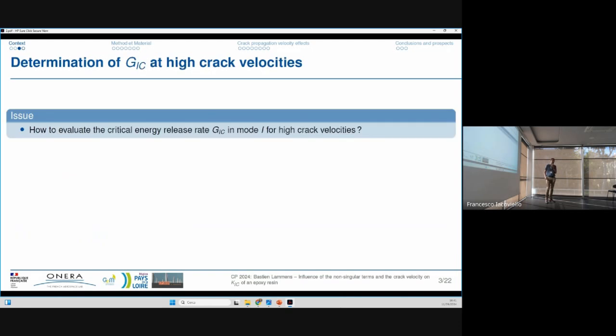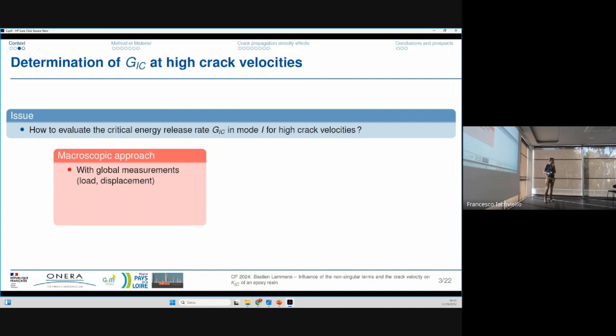So the question during my PhD was how to evaluate the critical energy release rate, G1C, in mode 1 for high crack velocity, because we want to have high crack velocity when we have a bird strike, for example. There are two main approaches that I can mention. The first one is the macroscopic approach with global measurements, load and displacement, and it allows us to determine the critical energy release rate, G1C.